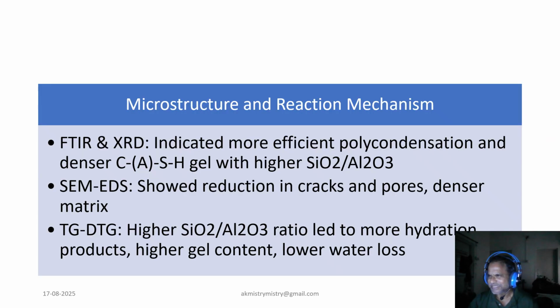Microstructure analysis revealed that a higher silica-alumina ratio promoted the formation of a highly polymerized dense gel network. FTIR and XRD confirm enhanced gel formation and reduced unreacted quartz and carbonate phases. SEM-EDS images showed fewer cracks and smaller pores. TG-DTG demonstrated increased hydration products. All these points towards a denser, stronger matrix promoted by optimized molar ratio and slag content.